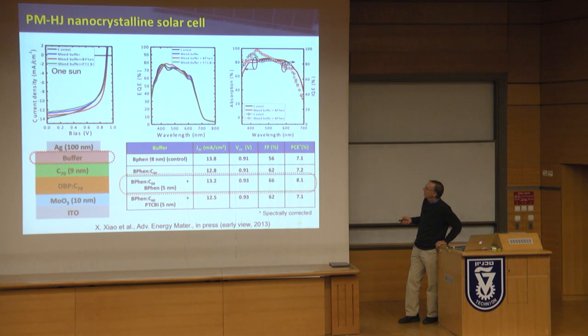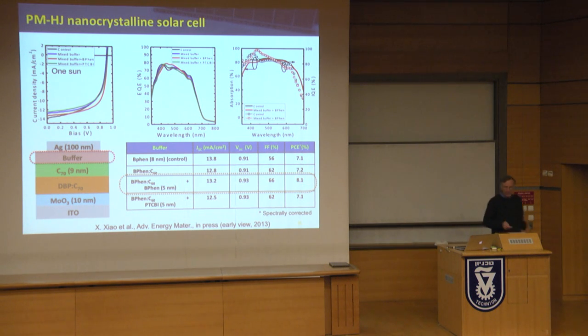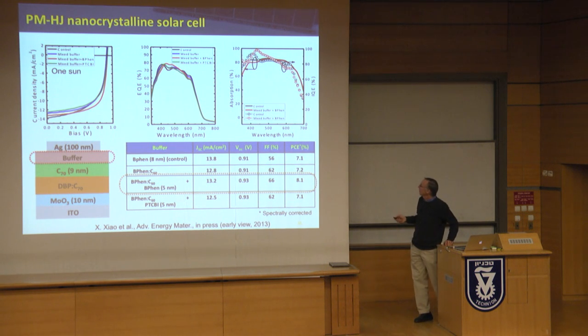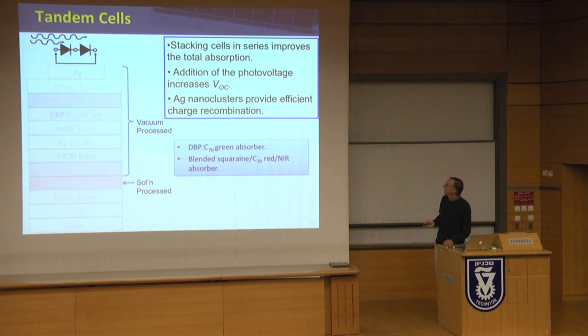This was the first buffer we ever tried back in the year 2001 or something like that. Back then we were making 1% and 2% cells, but if we use that buffer with these really good materials, we get to 7.1%, and here we get to 8.1% with this better buffer. So the buffer is really crucial. And you can see the quantum efficiency of these things, this is the internal quantum efficiency on this side, and this is the absorption percent on this side. And you can see that it's sitting up there in the 90% range. So this is looking pretty good. It falls off, unfortunately, at too early a stage.